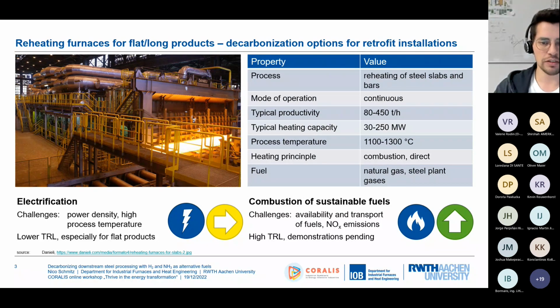And they do heat the product from room temperature or 400 or 600 centigrade up to 1250 centigrade typically. They are equipped with quite big heating powers between 30 and 250 megawatts. You can see, so really big furnaces here, really big powers. The heat is generated by direct combustion.